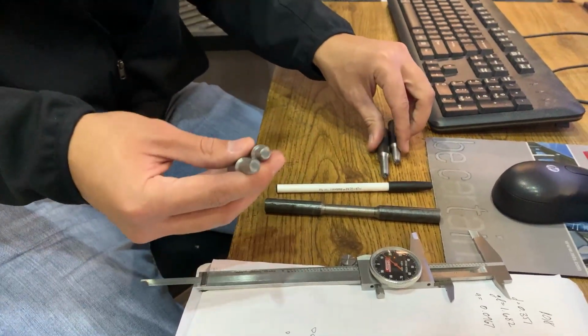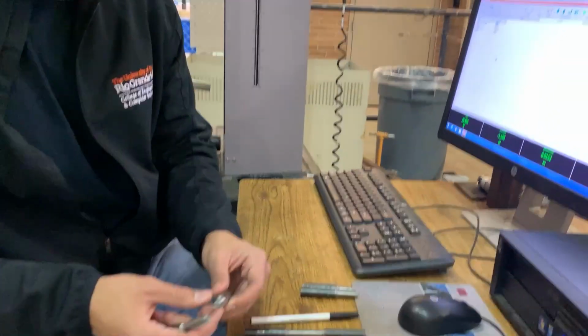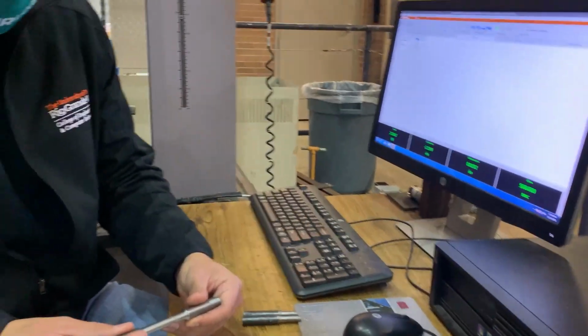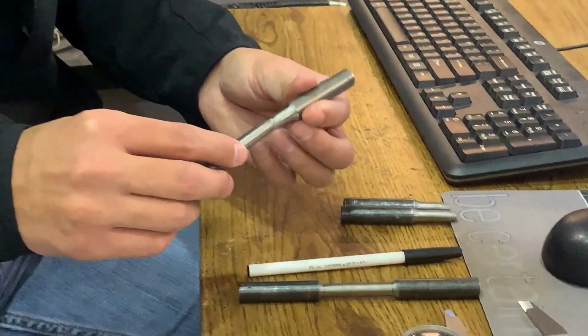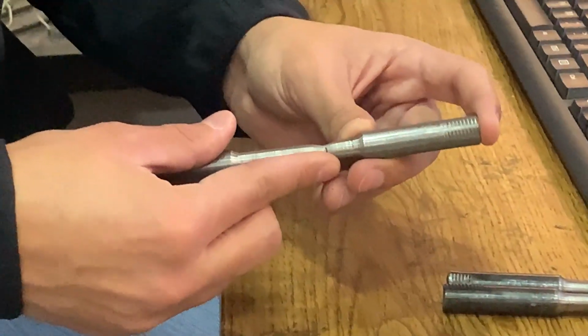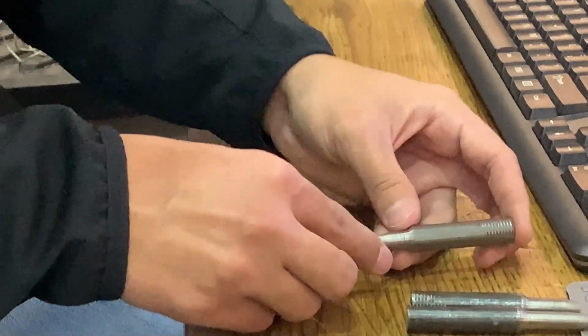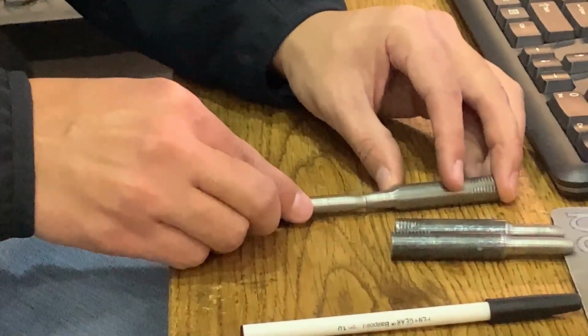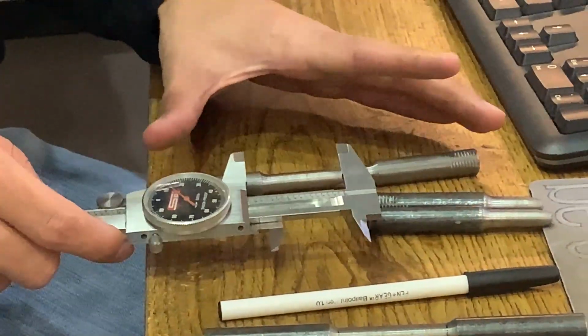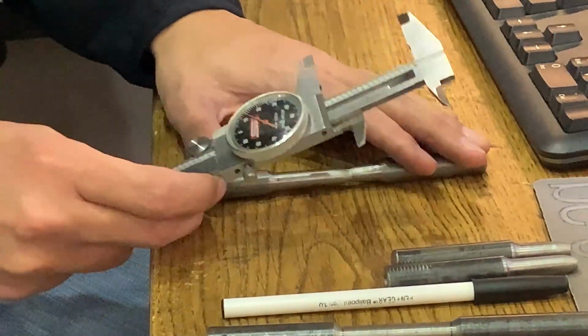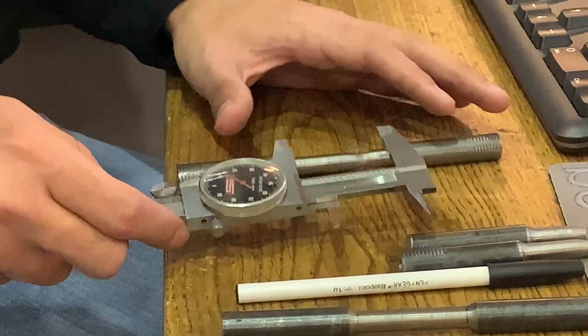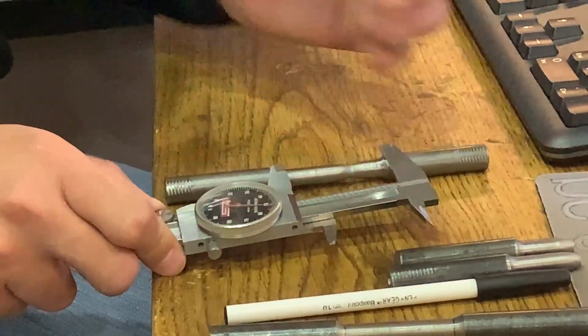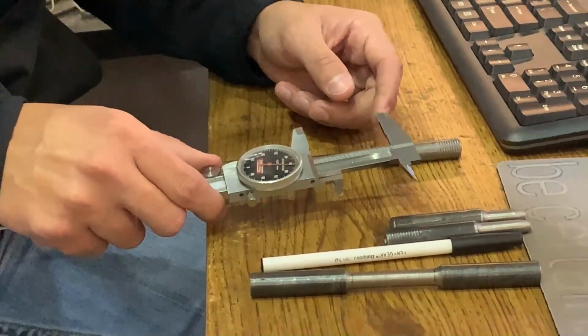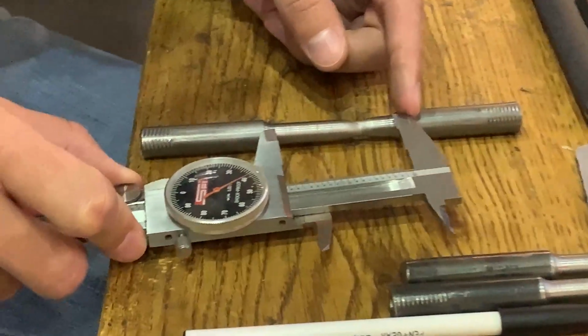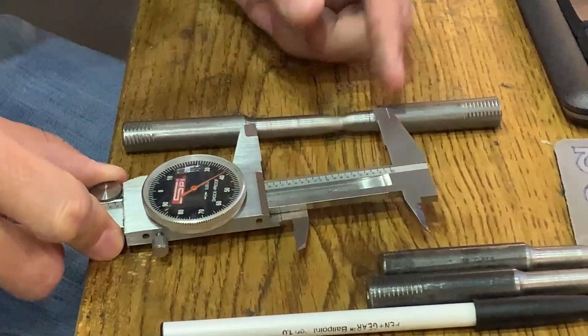Once we have our samples and we've looked at our fracture appearance and determined what type we are observing, what we need to do is try to place our specimens back to their original state here. Let me use the table. So we're going to try to line these up as best as we can. The reason, as I mentioned earlier, for making these initial marks is so after our testing is complete, we can come back and measure our gauge length, because we're going to need this second measurement to calculate the reduction of area, or percent reduction of area, ROA. So now we should be able to obtain our second value for the specific calculation in the equation. You do that for all your samples.